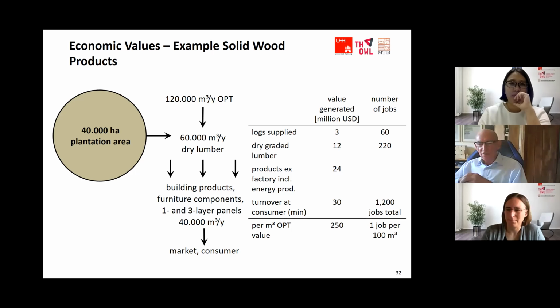We can produce building products, furniture components, 3-layer panels, 1-layer panels, about 40,000 cubic meters. And if we look at the value generated, this is at least $250 per cubic meter. And we have job creation of about 1,200 jobs from the 120,000 cubic meters of OPT. This makes about 1 job per 100 cubic meters of OPT processed, which is quite similar to very many industrialized countries. In Germany, for example, we have the same ratio, 1 job per 100 cubic meters of harvested